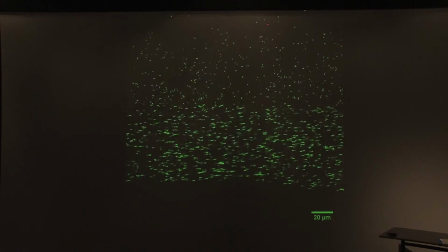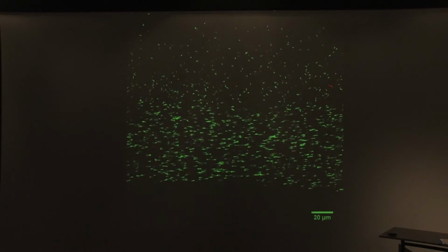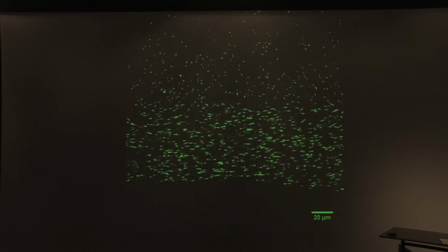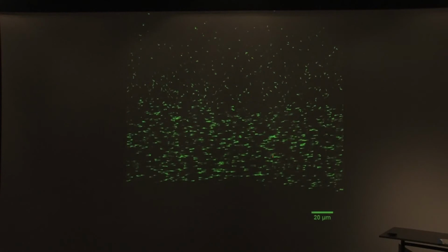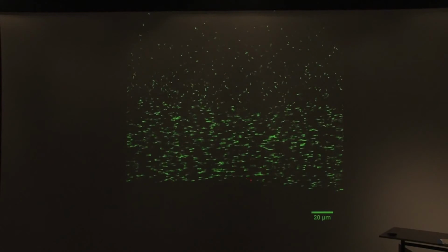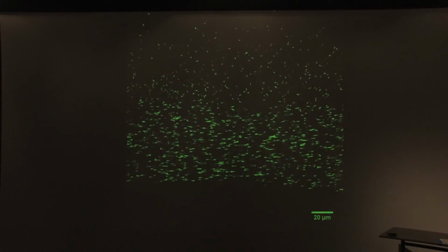On this picture, there's a density gradient. The concentration is increasing as we go down. And at low-ish concentrations, we've got fairly random motion, which is the equivalent to the isotropic phase. Then there's a phase transition here going into the liquid crystal state, and this is the liquid crystal state that we call a nematic state. And then further down, we have something that is much more solid-like, and it may be a solid or a glass, or it may be one of these liquid crystal states, a smectic state, which has some degree of translational order, and sometimes you can see layers forming, which is characteristic of that. Okay, thanks for that, Lewis.